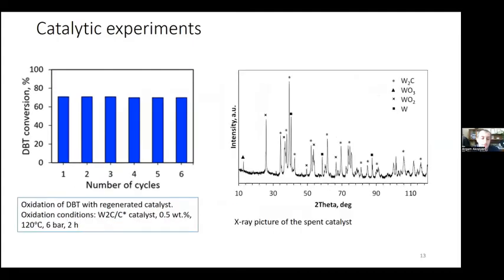To determine the possibility of reusing the synthesized catalyst after the reaction, the activated tungsten carbide was separated by centrifugation, and washed with acetone from the formed sulfone, dried at a temperature of 80 degrees Celsius under the reduced pressure, and used to oxidize a fresh portion of the model substrate. Note that no significant change in the activity of the catalyst is observed upon reuse. And the spent catalyst after six cycles of oxidation was analyzed with XRD. We would like to note that after the oxidation, the phase composition of the catalyst practically didn't change.